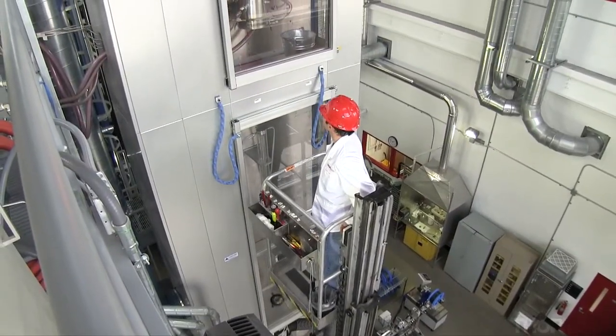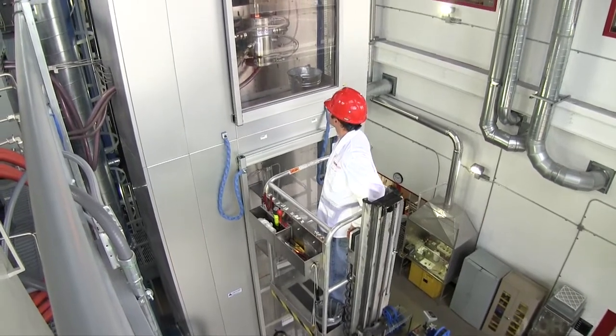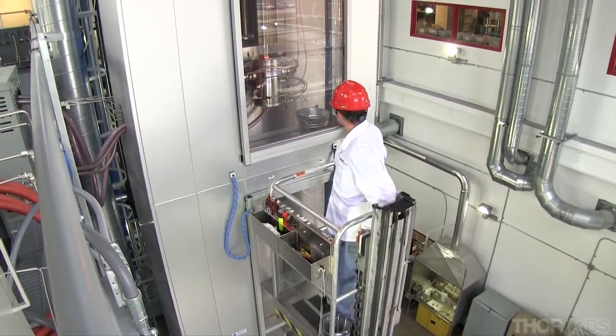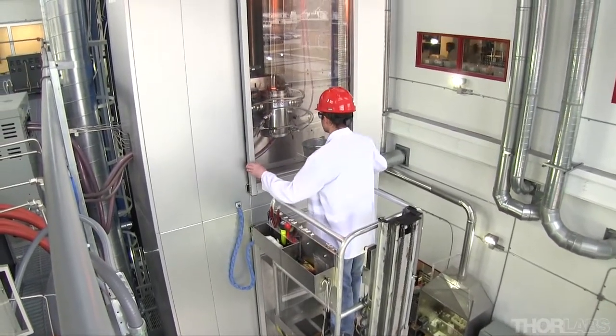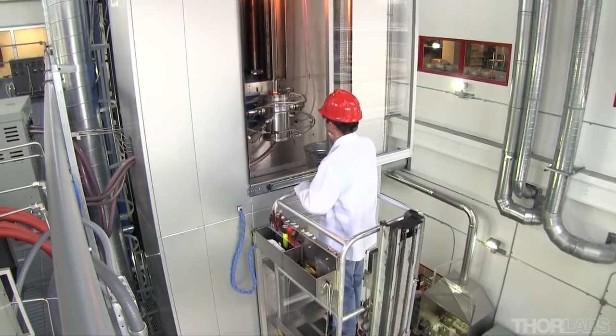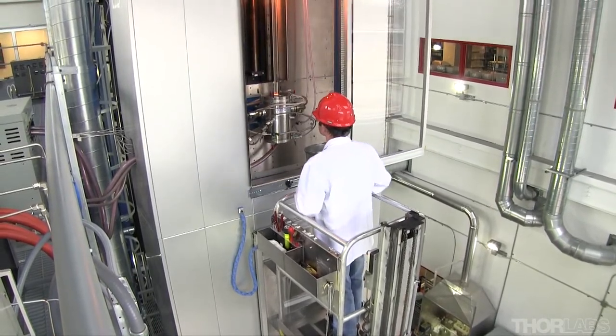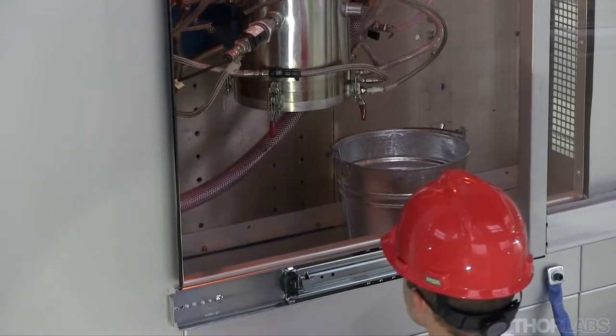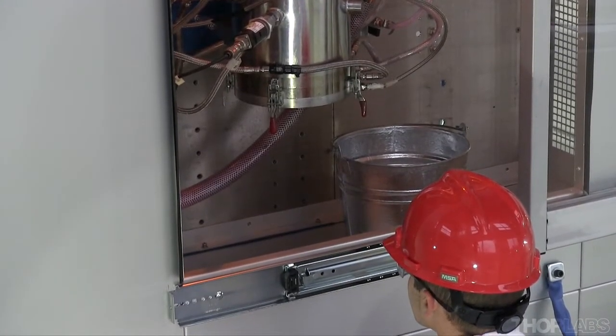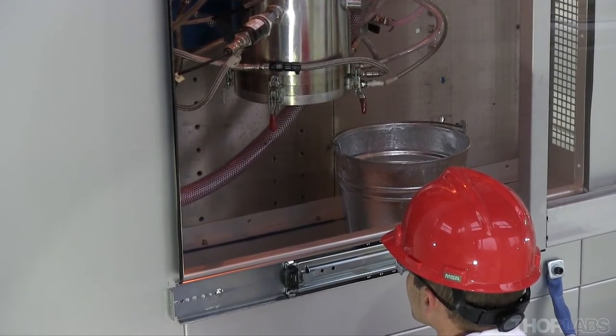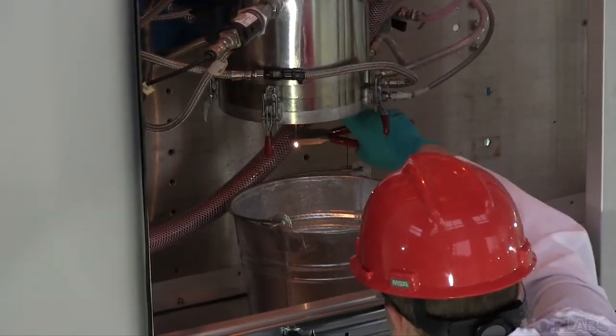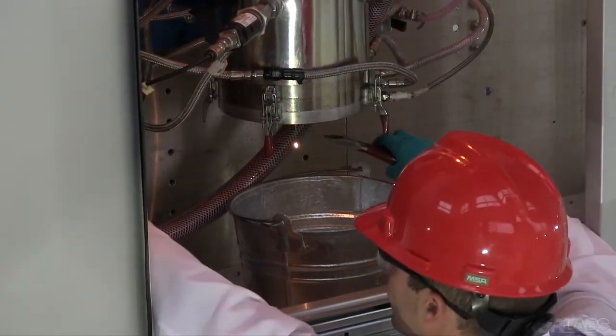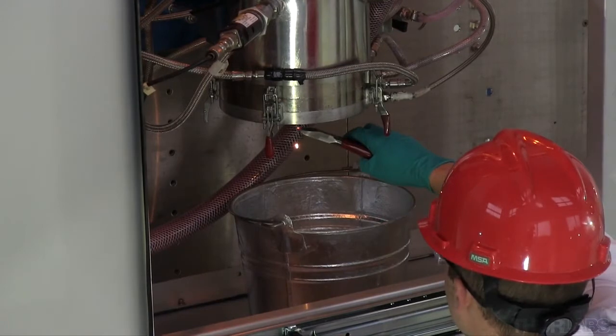The unit lowers the preform into the furnace where it is heated to 2,000 degrees Celsius. This graphite-resistance furnace has an element that surrounds, but does not touch, the preform. The graphite allows for an even distribution of heat around the glass rod. The fiber is pushed by the top feed unit and pulled, first by hand and then by capstan, down the length of the tower.